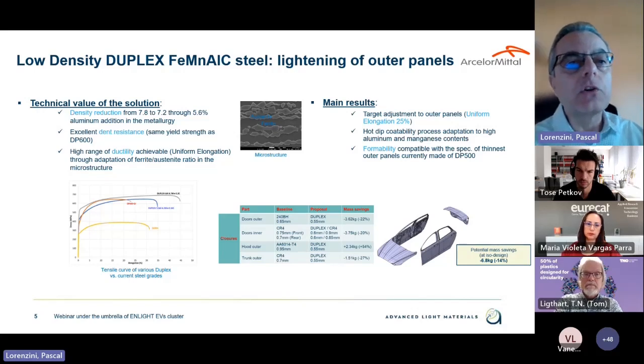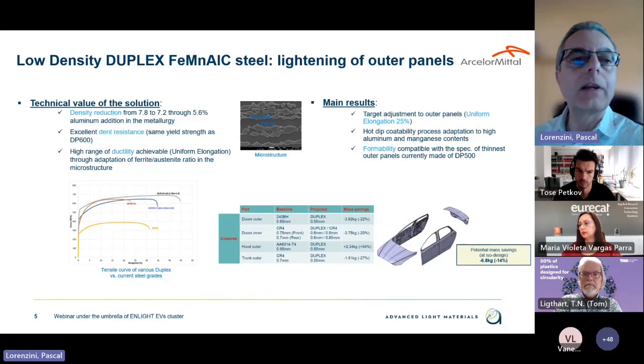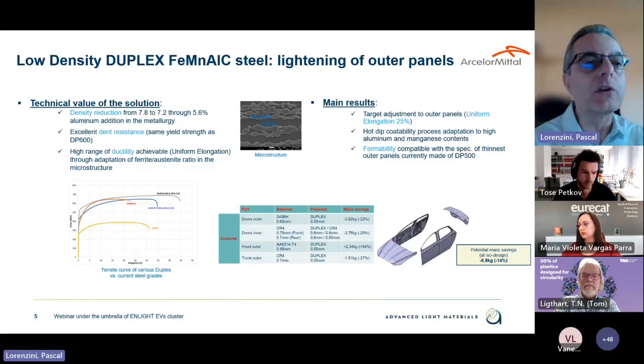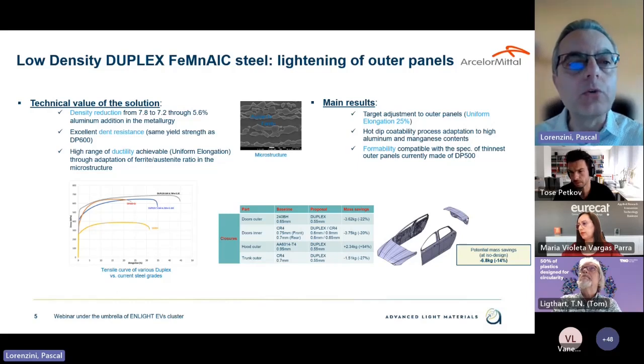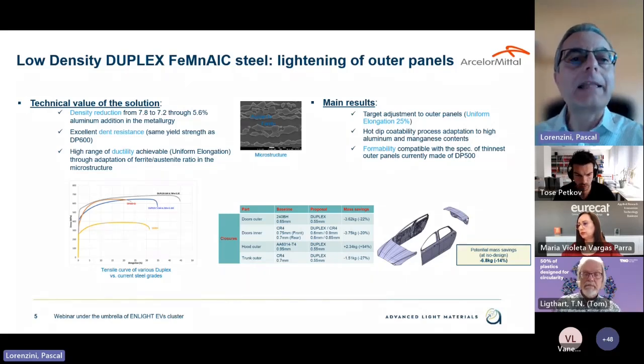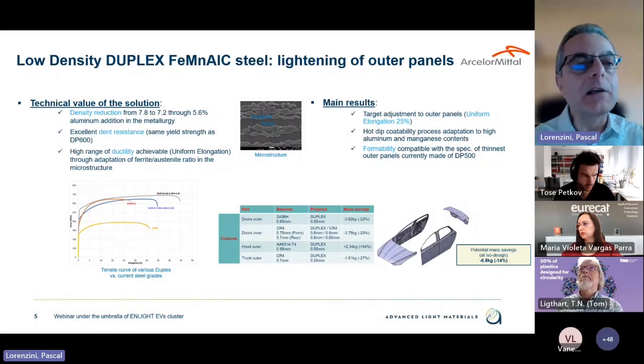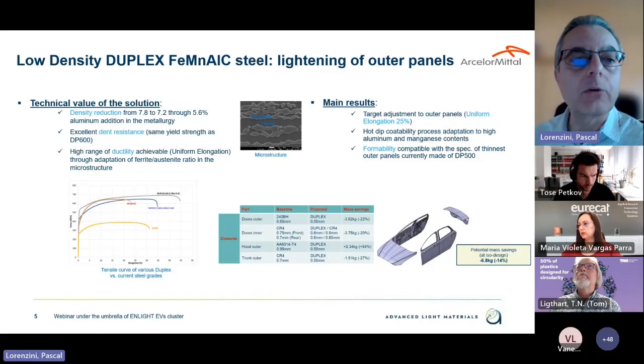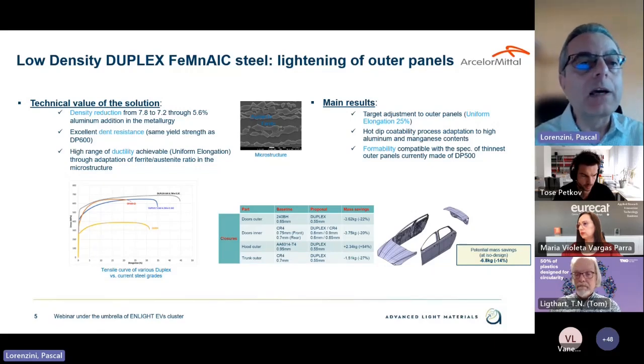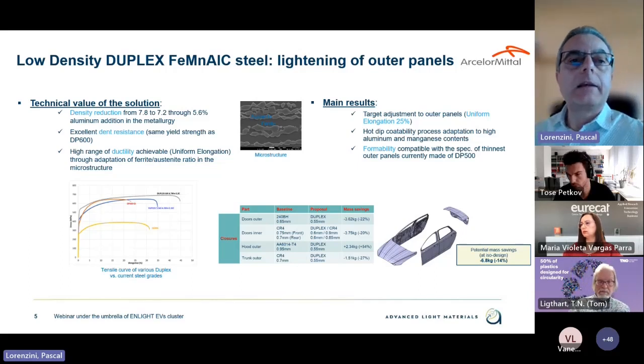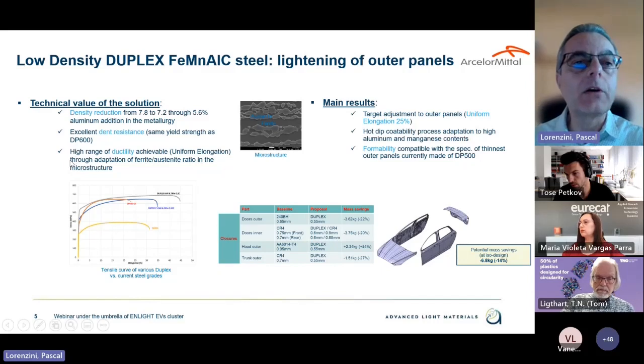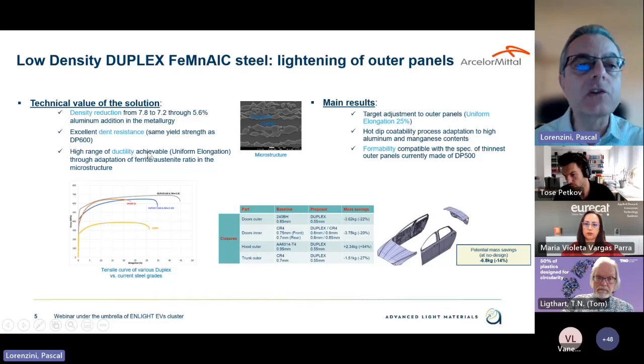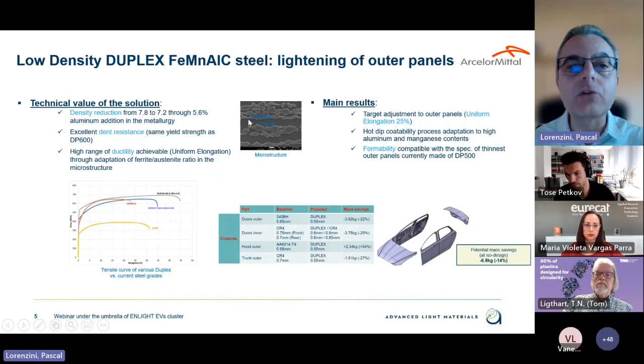Thanks to the addition of around 6% of aluminium in the metallurgy, we reach a density reduction to 7.2 instead of 7.8. And this kind of steel has an excellent dent resistance, which is a key property for outer panels, with the same yield strength as DP600. And this kind of concept enables us to adapt the range of ductility achievable through the adaptation of the ratio of ferrite versus austenite in the microstructure, because this is a duplex microstructure, that's why it's called a duplex